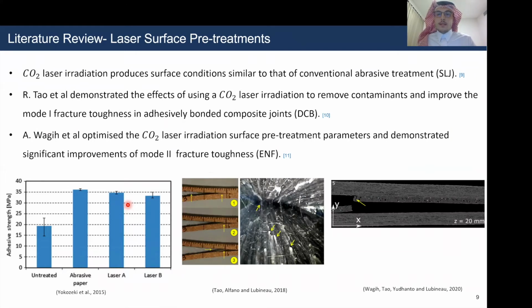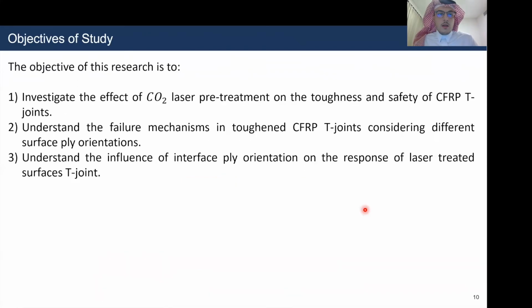Recently there has been some application of carbon dioxide laser irradiation, which produced surface conditions similar to that of abrasion in single lap joints. Also, locally in the KAUST laboratories, there have been studies on the effect of CO2 laser irradiation to improve the toughness of mode 1 and mode 2 bonded joints, in double cantilever beam and end notch flexural tests. Their improvements can be attributed to phenomena known as adhesive ligaments, fiber bridging, and secondary cracks in the adhesive. Therefore, I thought of applying this CO2 laser irradiation, which produced improvements in mode 1 and mode 2 and results similar to abrasion, to T-joint structures.